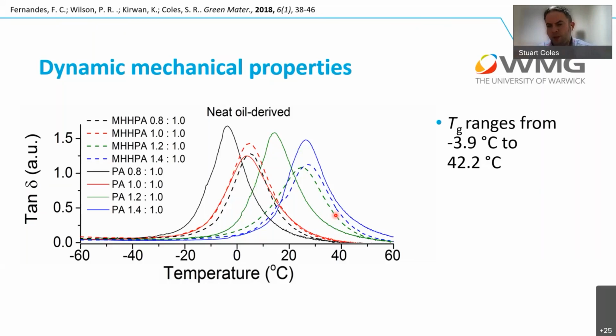And this was when we started to think about, well, these aren't going to be structural applications. We're going to have to do quite a bit of work on the Tg in order to get it into that range where structural applications become possible. And we did a lot of work. There's a lot of stuff contained within the student's thesis around trying to optimize these Tgs and push them up to 40 to 50, 60, 70 degrees. But ultimately we were unsuccessful in that area, and we expected to be unsuccessful in that area.